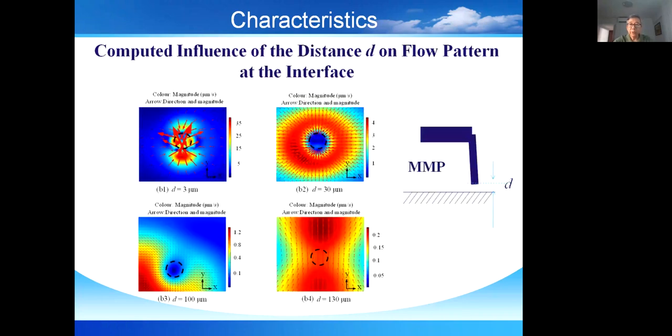We also found that the distance between the microprobe and the substrate matters. When the distance is too small, there is no concentration. When the distance is too large, there is also no concentration. It must be in a proper range to get the concentration effect. In our experiments, the range is from 10 microns to 120 microns.